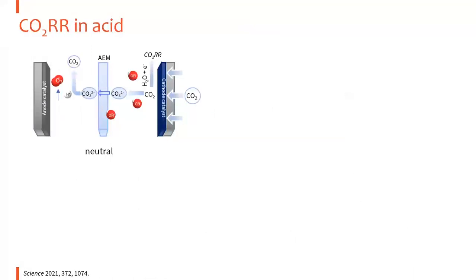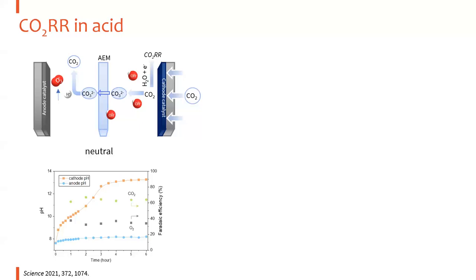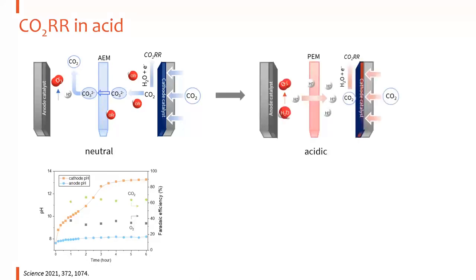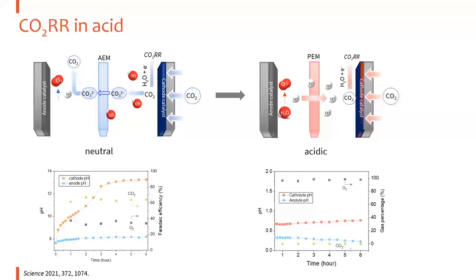Another strategy is that we can operate CO2 reduction in acidic conditions. We know that CO2 will react with alkaline, but if we can operate the reaction under acidic conditions, we do not have the alkaline OH challenge. Here is the schematic for neutral conditions, where we have the carbonate formation problem. That means we expect to generate CO2 at the anode mixed with oxygen, and the experimental data shows that we have a lot of CO2 together with oxygen. If we convert to acidic conditions, we have protons to transport through the membrane. We do not have OH ions and we do not have carbonate ions. And we found that, under the detection limit of our equipment, we do not observe CO2 at the anode side.